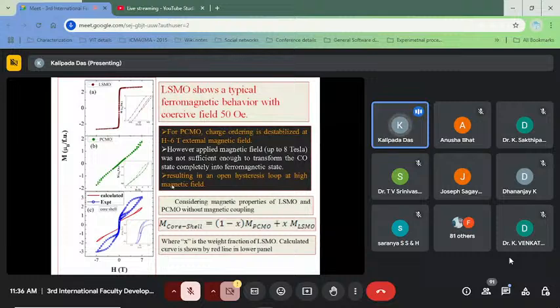Now we know from the preparation the weight percentages of the LSMO and PCMO. So if we add these weight percentages of LSMO and PCMO and generate the magnetization versus field response, that will be the red curve, but experimentally we get the blue curve. Hence, from this study we can conclude that LSMO and PCMO spins interact. They are not distinct. Due to the presence of LSMO within the PCMO matrix, the magnetic state of the PCMO is changed.